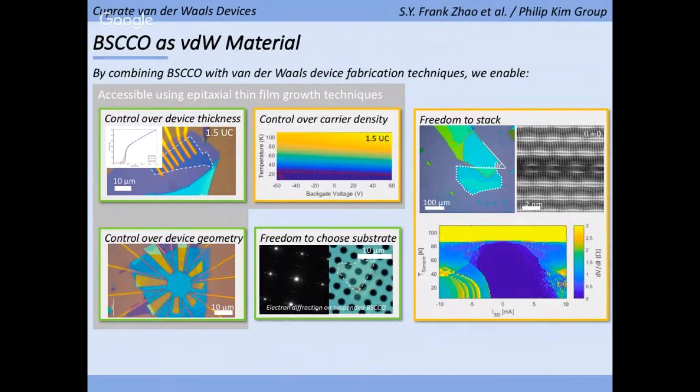Right. So what's interesting about this crystal actually is that it sticks very well to silicon oxide substrates, but it doesn't stick so well between the bismuth oxide planes. So actually, the usual trick with graphene is that you can always pick up your graphene with a hexagonal boron nitride. There's basically no exception. You can tear your graphene this way. But here, this BN doesn't work at all. It just doesn't stick at all. And if you use another BSCCO, actually, it also doesn't work. So for some reason. Right. So I don't know if that's from a surface degradation or if there's something deeper going on.